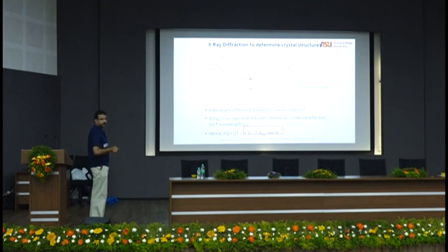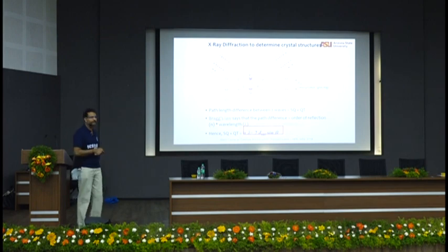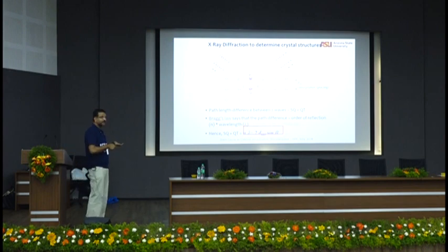Good with that? If I know the angle of reflection, or angle of diffraction of the wave, can I not find the extra path the wave is traveling? Simple trigonometry, 6th, 7th grade trigonometry, you can do that. You can find out what SQ and QT are. You will see that SQ plus QT is equal to 2 times d sine theta.